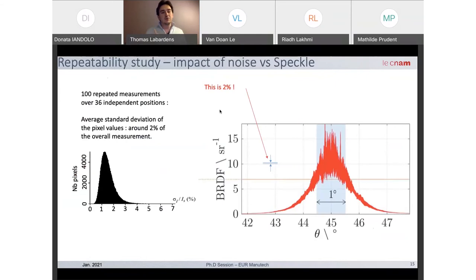So we repeated 100 times the measurements over 36 different positions on our samples. And we saw that the average standard deviation for the pixel values in our measurements was around 2% of the overall measurement, and you can see on the image on the left what 2% represents. It's really small compared to the high fluctuations that we have. So since this noisy effect doesn't come from the system,